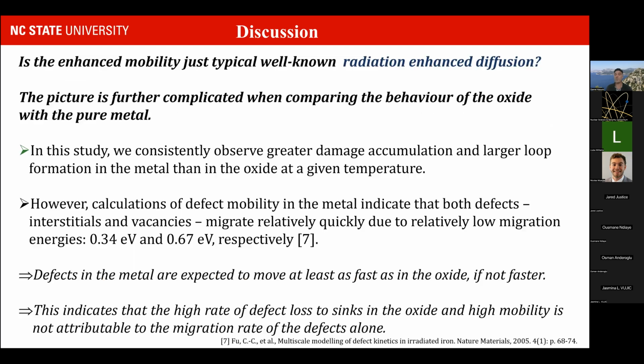But that tells us about an enhanced mobility of defects in the oxide. First question that we have is, isn't it just radiation-enhanced diffusion, which happens everywhere? Specifically, it happens anytime that you have irradiation in your material. The point defects' diffusivity is going to be affected and usually enhanced. But this picture is not that simple. It's actually complicated by the fact that when we compare the oxide and the pure metal, we don't see the same behavior, because radiation-enhanced diffusion will happen also in the metal. In fact, the migration energies for the interstitials and the vacancies are very small. So if the loss of defects was due only to radiation-enhanced diffusion, it should happen in the metal as well. So that's not the case.